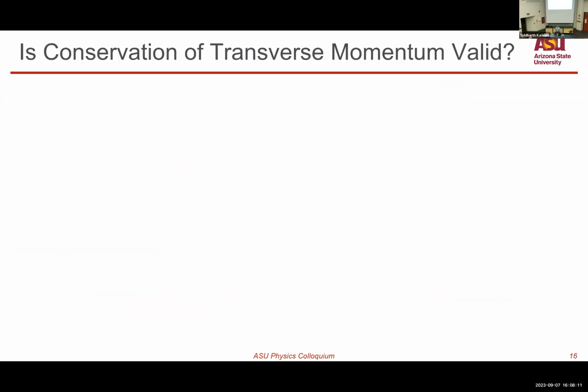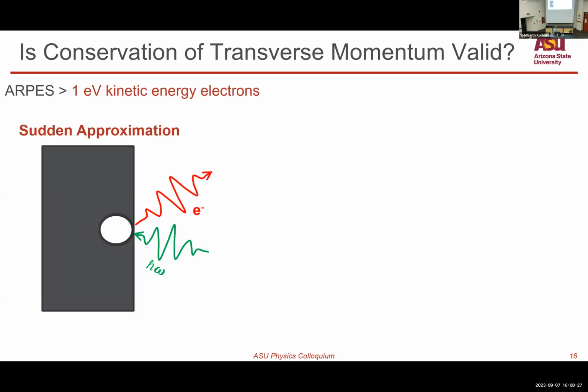Okay, now that sort of brings us to the question. I've been talking about this conservation of transverse momentum, where electrons conserve the transverse momentum when they're emitted, quite a bit, but is that even valid? Now, if you would ask many folks, they would say, yes, it is valid. And in fact, it is the basis of angle resolved photoemission spectroscopy, which is a well-established technique where we use high energy UV or X-ray photons to extract electrons with energies greater than a few electron volts and measure the energy and angle at which these electrons have come out to obtain information about the band structure. And this technique relies on conservation of transverse momentum.